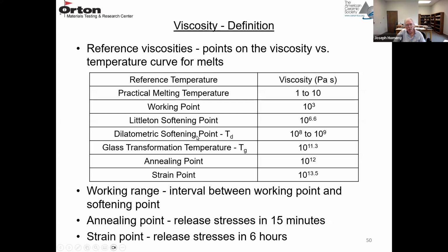Dilatometric softening point, TD. That's when you measure a softening point in a dilatometer, and you actually have some load or stress on the sample. So this softening point, when you use a dilatometer, is going to be a little bit higher than the ASTM standard Littleton softening point. So 10 to the 8 to 10 to the 9.